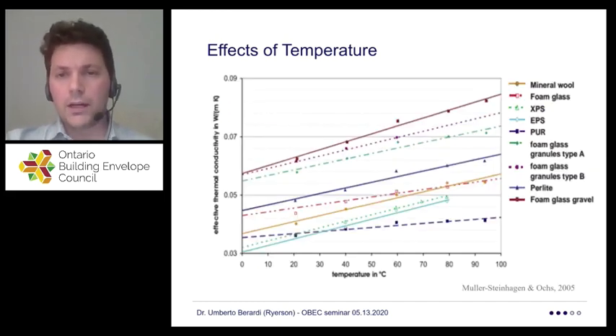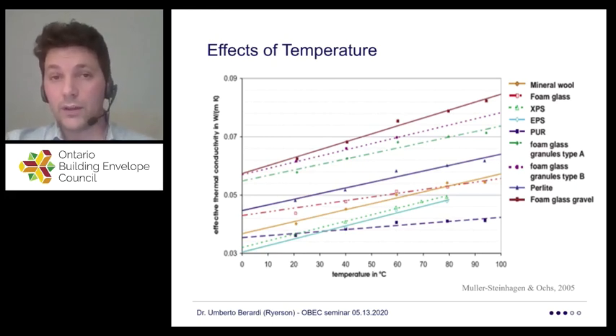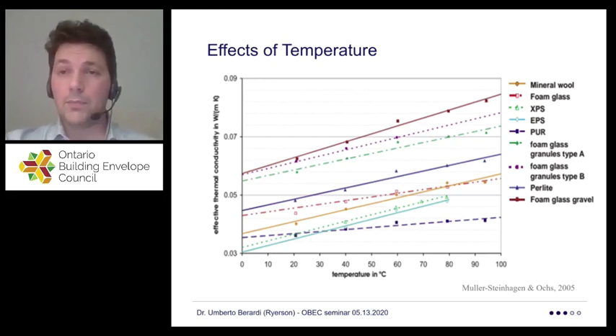So this is a graph that has been around for 15 years, so quite old, but it gives you a snapshot of the temperature effect on thermal conductivity. You see there are some products that have a curve that is a bit more flat, others a bit more significant, but all the products, especially mineral wool and foam glass, have a linear dependent curve. Period. This curve is real. If you're only designing an enclosure in the middle of Washington, D.C., probably your fluctuation is not significant, and your analysis will not be affected by a big error. But if you're designing for conditions that are quite different from 20 Celsius, then the error may become bigger.